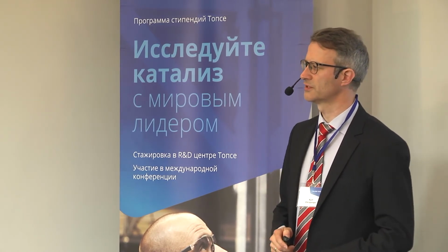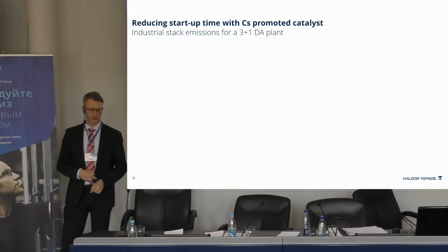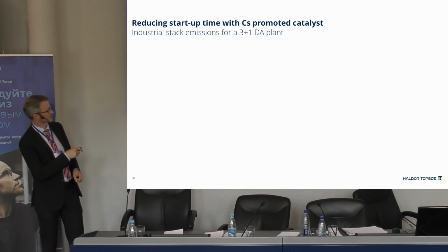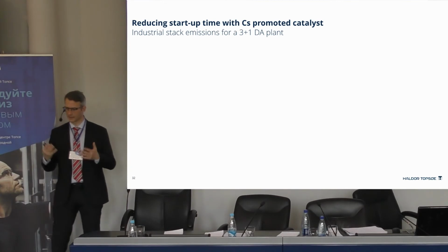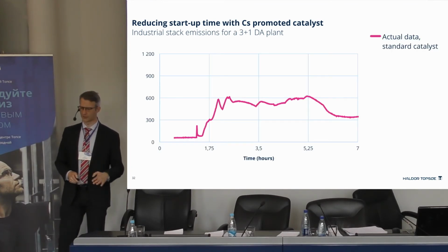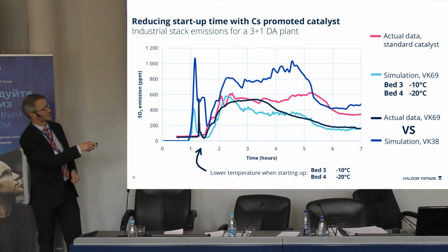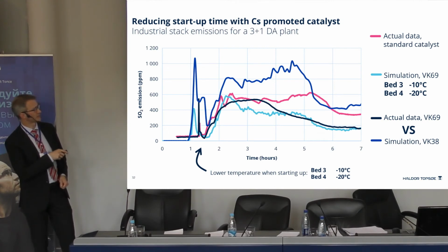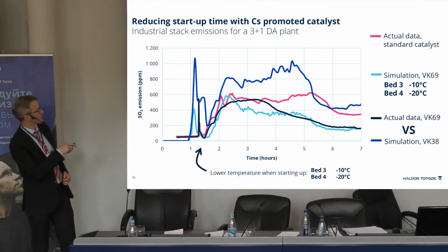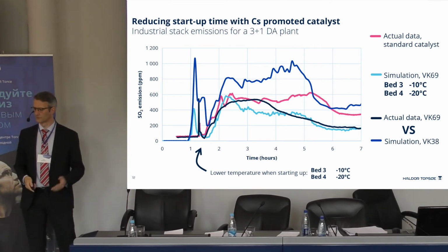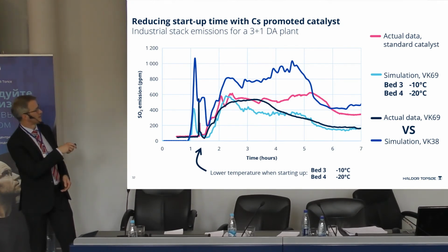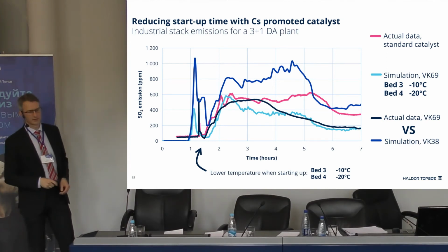Another example is to use the cesium-promoted catalyst, a low-temperature catalyst, to keep startup emissions down. In this case, a double absorption plant in industry had this startup emission. You can see, as a function of time, some 500-600 ppm SO2 going to the stack when they started up. However, they wanted to reduce bed temperatures because then they could start up faster. And that's good business for them if they can start up faster and start production. So how could we reduce bed temperatures and have a faster startup? Well, we could put in VK69, which is a cesium-promoted catalyst that works better at low temperature, and we predicted this. This is a model calculation based on their startup data to say, if you put in this catalyst, you will get the blue curve. They installed the catalyst, and they measured this dark blue one, and you can see that's not too bad predicted for this plant's startup.